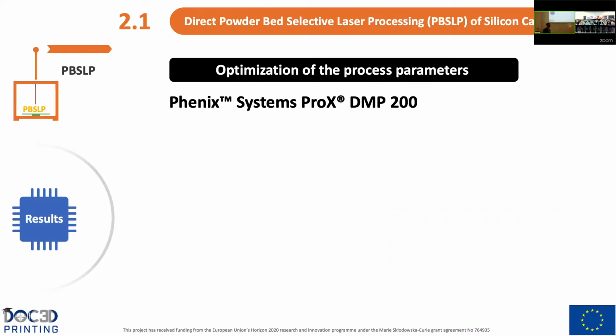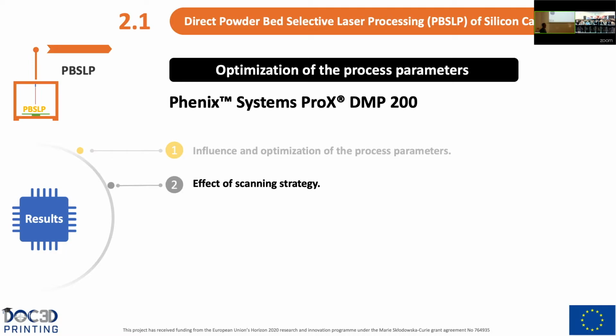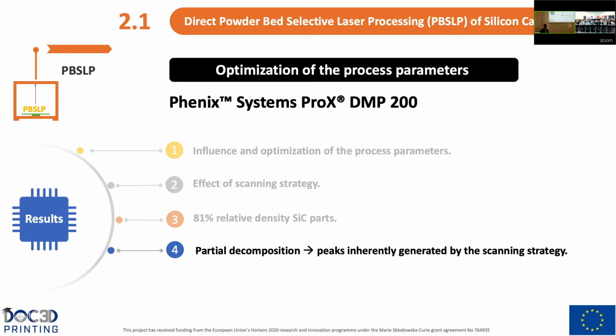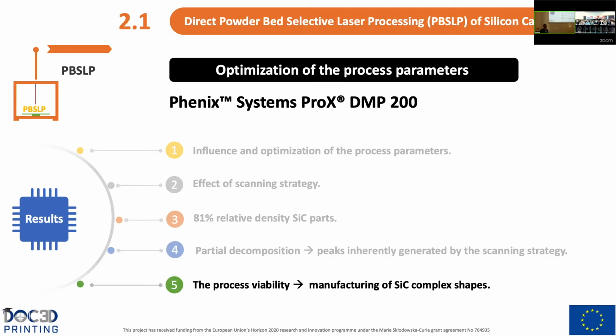So from this part, we can draw the following results. We have studied and optimized the process parameters of the powder bed selective laser processing. We have studied as well the effect of the scanning strategy. We have obtained 81% relative density silicon carbide parts. We have observed some partial decomposition during the process due to some peak energy generated by the scanning strategy. And finally, we can confirm the process viability, because now we are able to manufacture silicon carbide components.